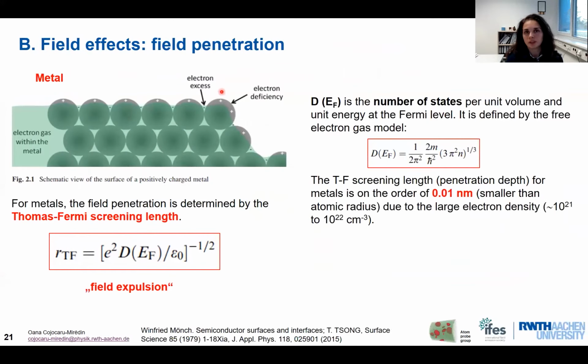So let's speak about field penetration. And I think this is a very important concept, especially for the semiconductor material. Let's start with the metal, because this is our basic material that we work with in our lab. So when we speak about field penetration for the metal, we speak about the screening phenomenon. This is determined typically for metal by the Thomas-Fermi screening length. And the formula is given here below.